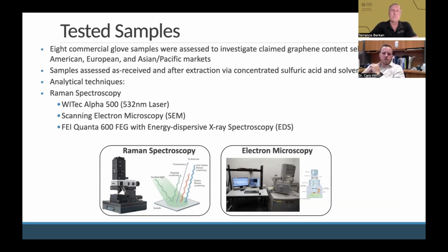Selected from different markets around the world, representative samples, I believe, from different sectors. We extracted the gloves, we tested them as received, we looked at the fibers as received, looked at the rubberized material as received, and then extracted from the fibers themselves, performed dissolution through acid or solvent extraction in order to retain the graphene or graphene oxide. Graphene and graphene oxide would not be dissolved by these extraction methods, but the polymeric fibers would.